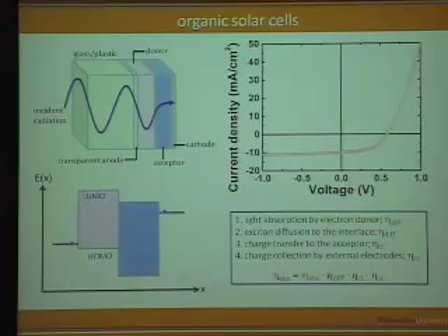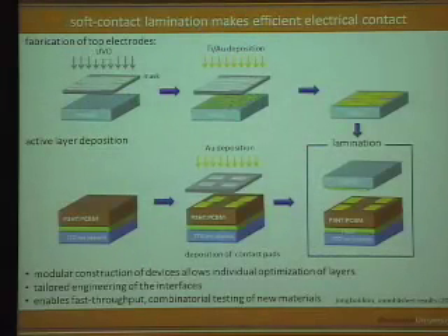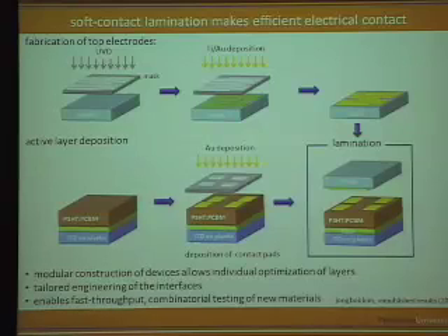They're frequently mechanically and chemically fragile. And so if you're using the same technologies to put down and pattern the cathode, for example, on the organic layers, you can potentially damage the organic layers. And so what we'd like to focus on is come up with non-invasive processing technologies to make these devices. So here in this example, I'm showing you how we can laminate to make organic devices.